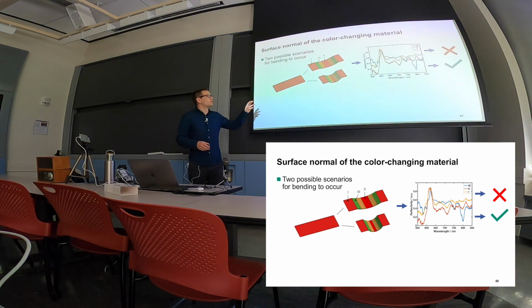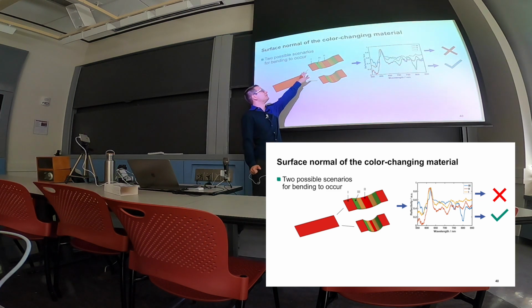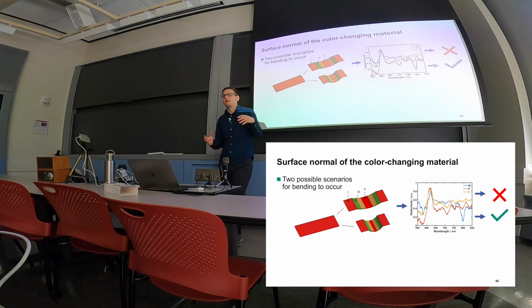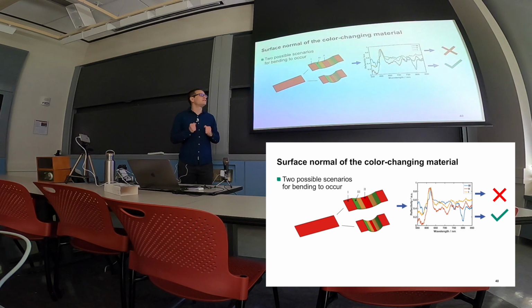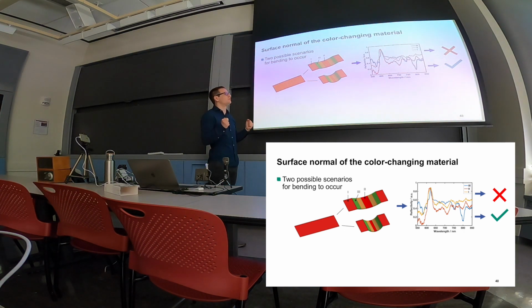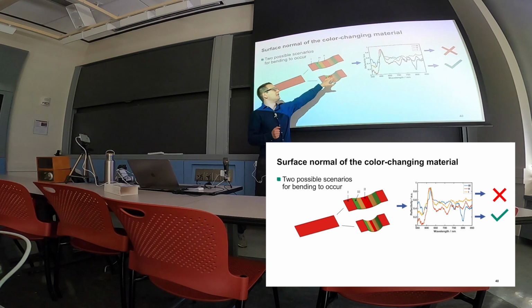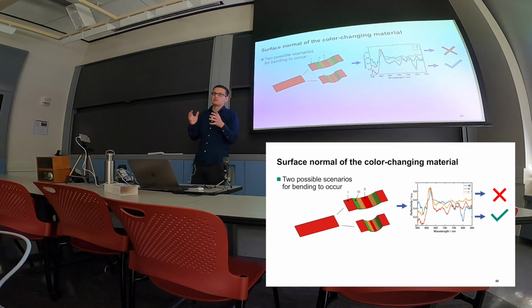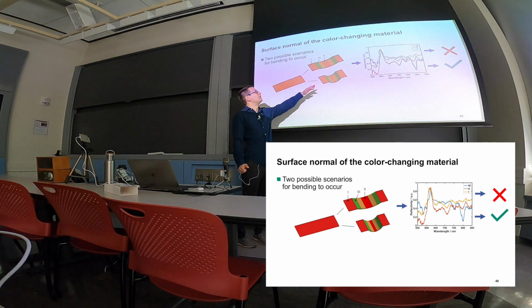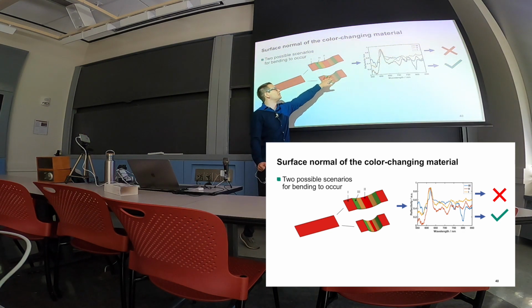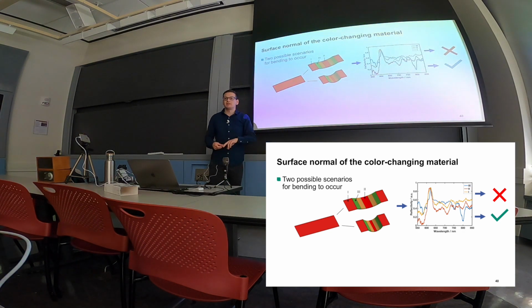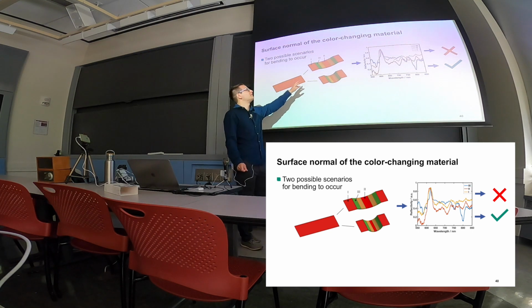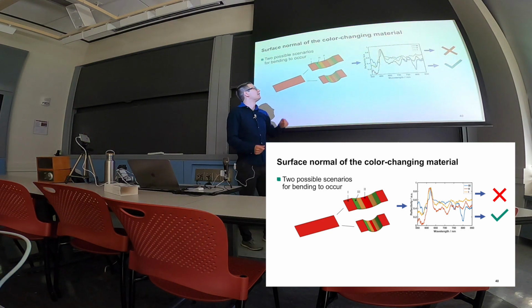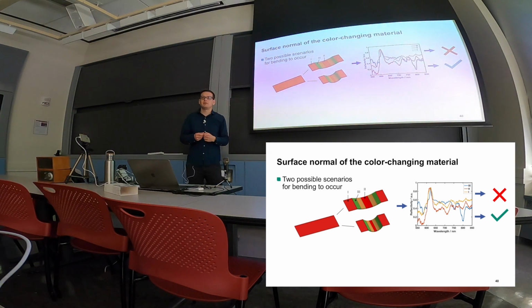And so the first way that could happen is that the soaking process of the vacuum is so strong that the color changing material will be soaked into the cells and therefore changes the thickness of the layer due to stretching. Or the other option is that it will just be soaked in, and due to the deformation of the metamaterial, it will have a color change only by the viewing angle under which we observe the cell. And so when I observed this object from different angles and always saw a red color occurring, I knew that the first option, what we see at the top side, cannot occur, because then we would have a different peak wavelength reflecting.